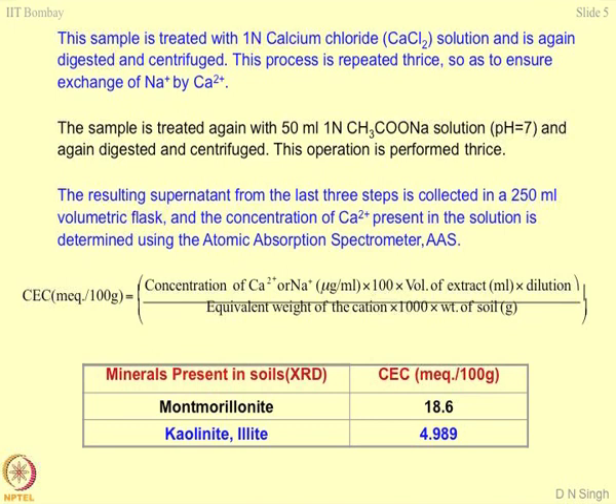Just to give you some idea about the CECs of different minerals, and hope you will appreciate why some minerals are very active and why some minerals are not active, this table gives you a clear picture. If you find out the minerals by using XRD, X-ray diffraction technique, for montmorillonite the CEC is 18.6, and for kaolinite and illite, CEC comes out to be approximately 5. So almost it's 3 to 4 times difference between the cation exchange capacity of the clays themselves, alright. Kaolinite and illite are clays and montmorillonite is also a clay mineral. But this is one of the reasons why the water absorption capacity of montmorillonite is much higher than kaolinite.